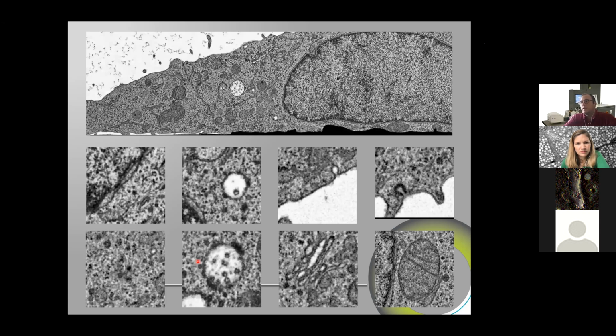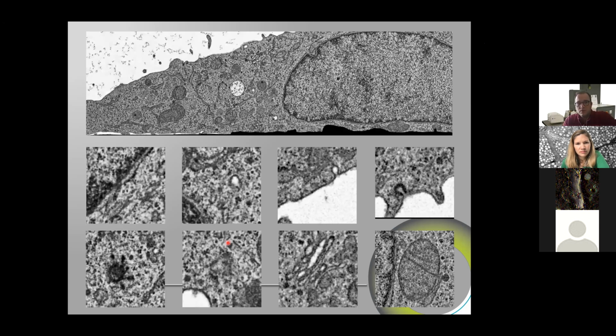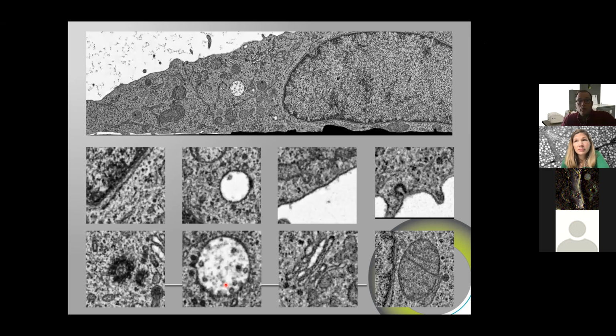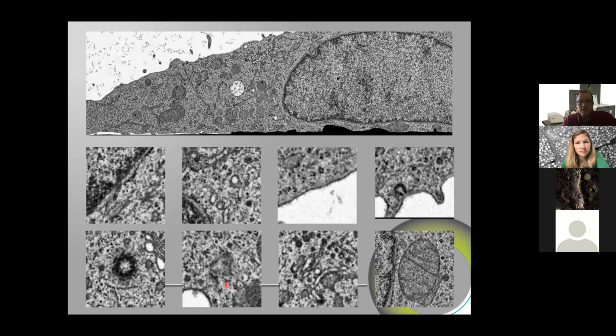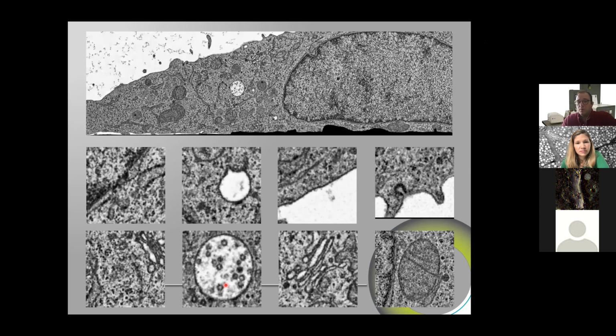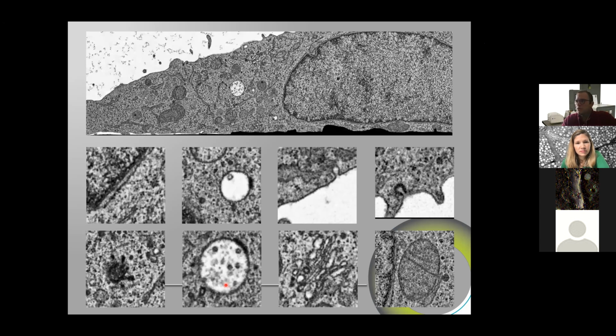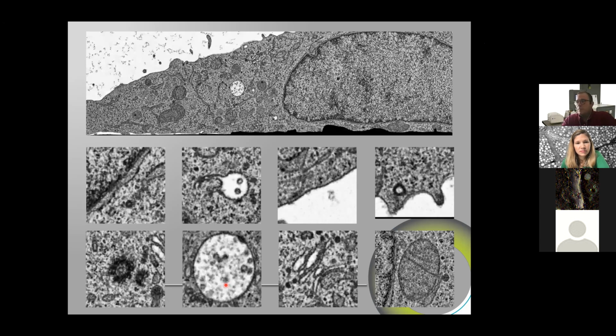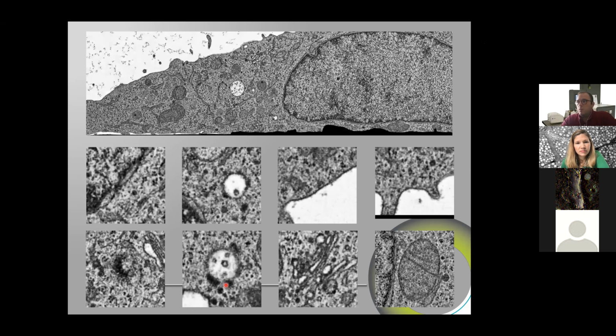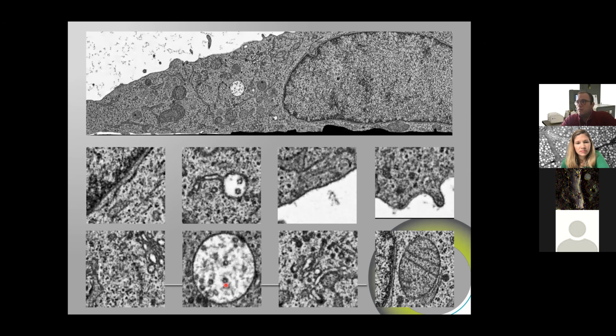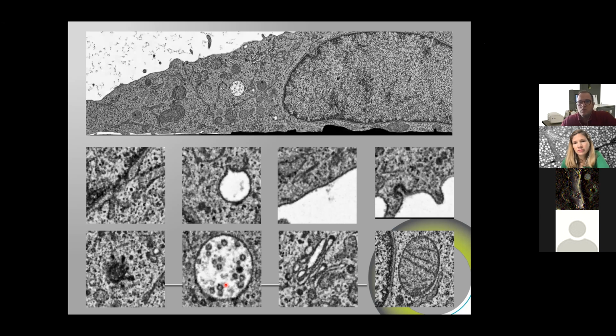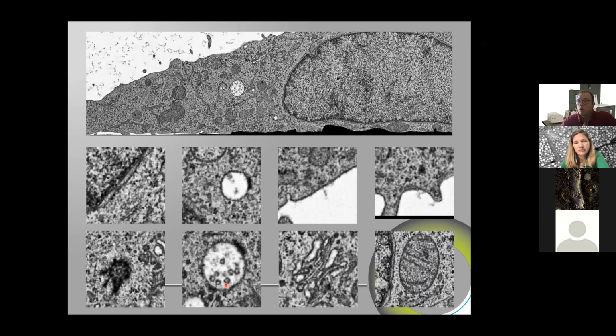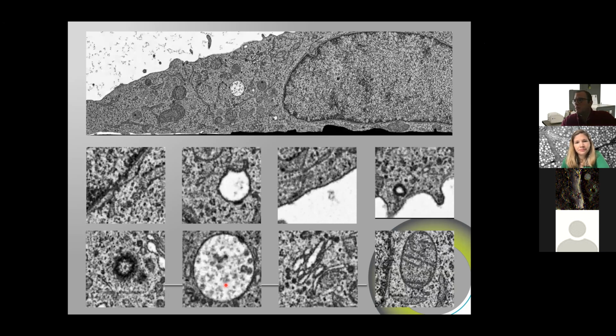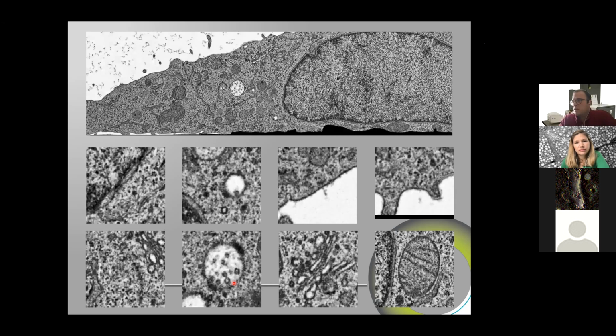So we can obtain a very fine resolution, although we have only 0.05% of uranyl acetate in the cocktail and 0.1% or 0.01% of glutaraldehyde. So basically, although we have what we consider as being very close to no contrasting agent, we already have a very high contrast in the structures. And that was surprising to us.